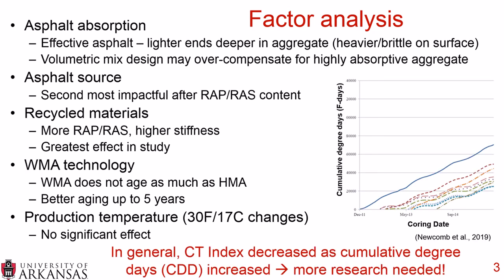What they did is that they took cores on the 9 sites, that's the graph on the right, and they took cores at various cumulative degree days. And in general, they found that the CT index, which is found from the IDEAL-CT test, decreased as the cumulative degree days, or CDD, increased. However, they said that more research was needed, which I always appreciate.